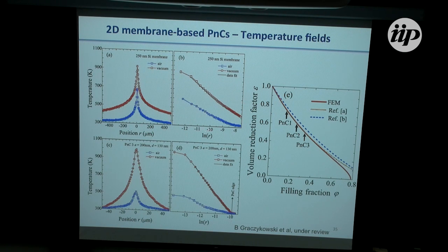Here the position of a temperature with respect to the logarithm, the temperature field for another sample, and we put here the volume reduction factor for the 3 geometrical arrangements, which corresponds to this filling fraction. So there is a dependence on how much material you have left, the volume reduction, the surface to volume ratio, but it's more illustrative to see this.